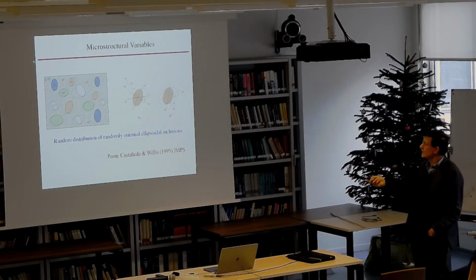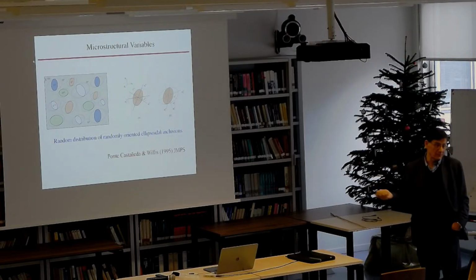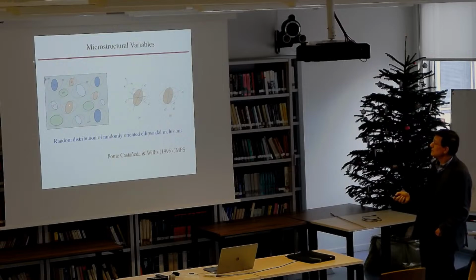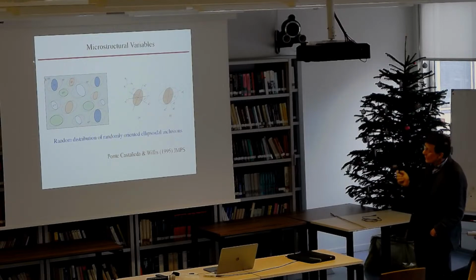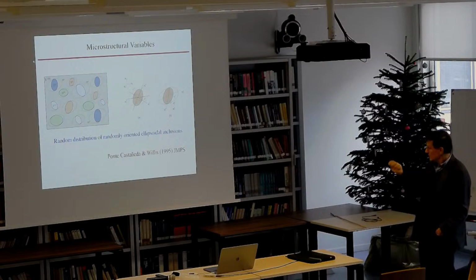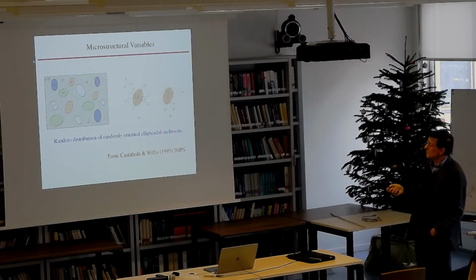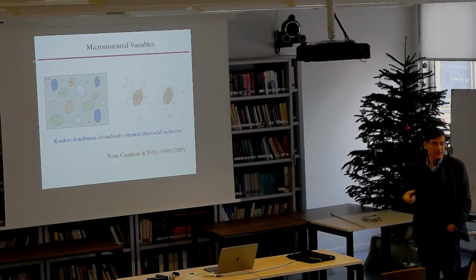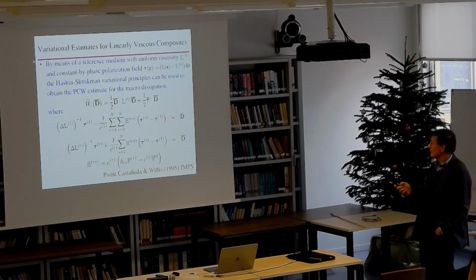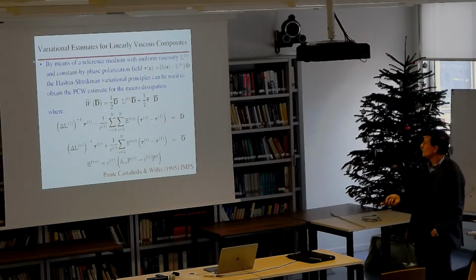And I'm assuming for simplicity that the distribution of all the inclusions is the same, okay? But you don't have to do that. The distribution of inclusions could be different, but there is a requirement that comes from the definition of these pair correlation functions that the distribution of one family of inclusions relative to the other family has to be reciprocal, meaning that the distribution of this family with the other family has to have the same shape. So that puts some restrictions, and of course those restrictions are automatically satisfied by assuming that the shape of the distribution is the same for all the inclusions.